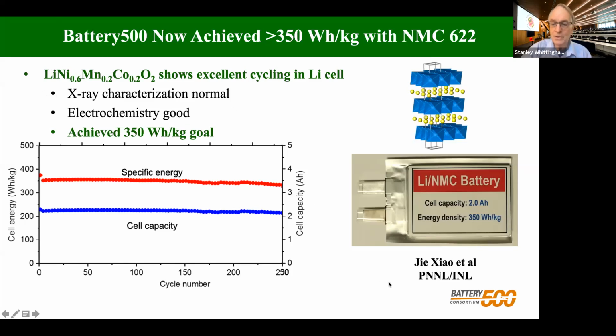So my ex-student Jie Xiao built batteries of this material, which were then tested at Idaho National Lab. And you can see the stability of these materials is very, very good. And these exhibited 350 watt-hours per kilogram at a cell capacity of 2 ampere hours. And this was really the goal of the consortium for its second year. And there's no fudging the data because these are pouch cells we used. These were weighed and the volume measured, so we know exactly that these are real data.